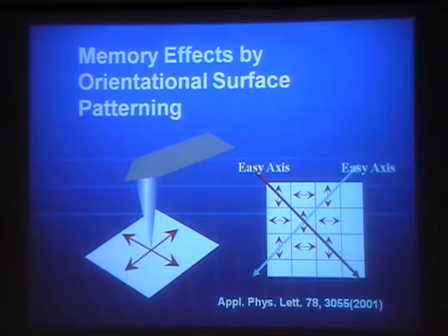So because locally the orientation remains the same, what is different is the topological connection across the surface, depending on the way you reverse the orientation. So these two diagonal axes give completely equivalent, energetically equivalent states. So these two are metastable, equally stable states.